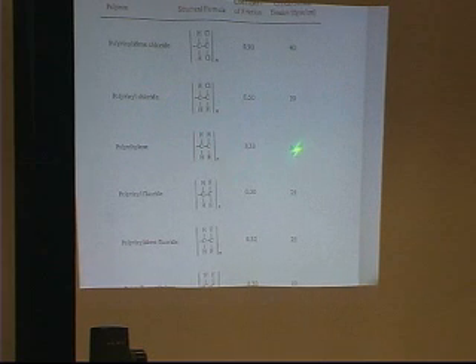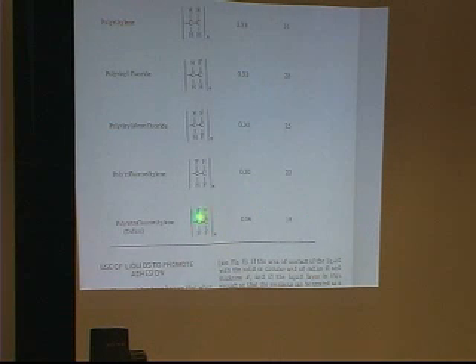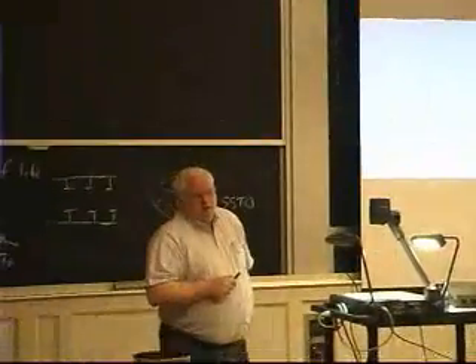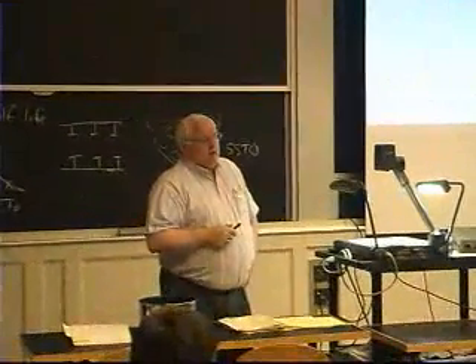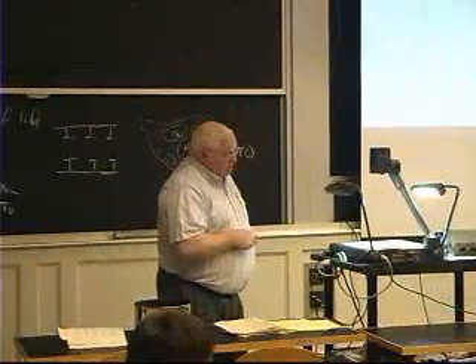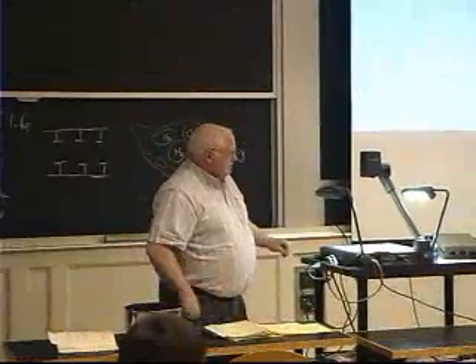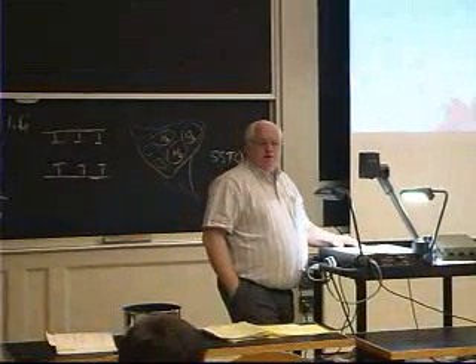If water's 72, this is 40. Okay, and then come down here. Well, here's polyethylene. It's 31, and so 30. Well, 36 is half of the 72. And the lowest surface energy of anything is carbon backbones with fluorines. All fluorines. This is 3 fluorines and a hydrogen, which is 22. Teflon is 18. Okay, a quarter of the surface tension of water. There actually are some others that are around 16 or 17, but they tend to be gases rather than solids. But Teflon has the lowest surface tension of anything.